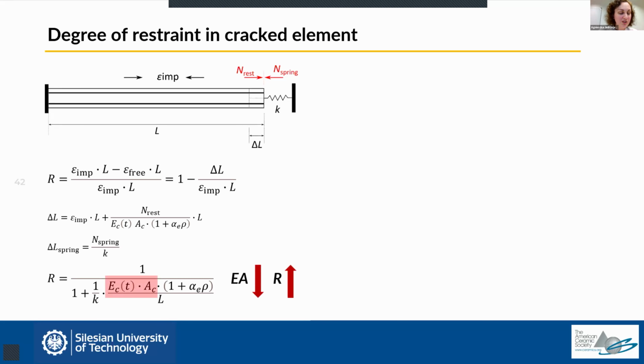So one of the common misconceptions is that due to the cracking, the element becomes less stiff, which means it will have a smaller stress. On one hand, this is true, but there is also a counterbalancing effect of increasing restraint. So we may not be 100% confident that the resulting stresses in the cracking element will be lower. They might still be the same or even higher.